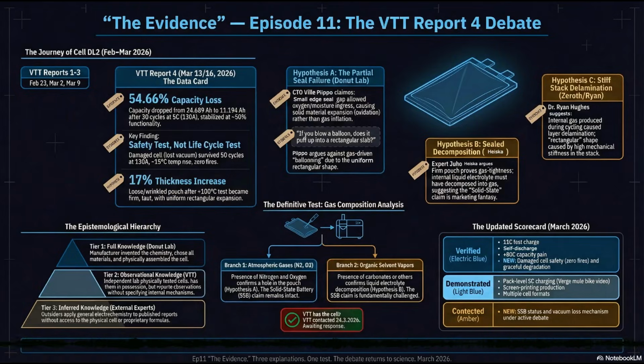The first and most dominant factor is contact loss. Yeah. In a true solid-state battery, the solid electrolyte only conducts ions where it is physically touching the solid electrodes. Because there's no liquid to bridge the gaps. Exactly. Therefore, solid-state batteries rely on massive mechanical pressure, sometimes tons of applied pressure, to keep those solid microscopic layers mashed intimately together. And the moment the vacuum was lost at 100 degrees, that essential mechanical compression vanished. Poof, gone. Without the vacuum compression pulling the pouch tight like a corset, the internal layers were vulnerable.